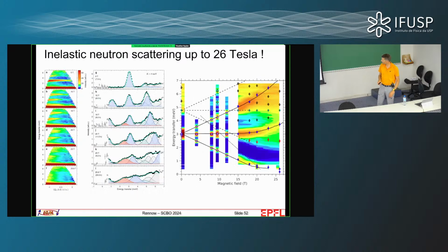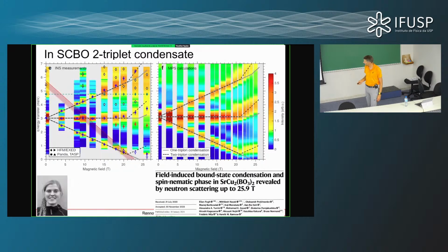We were able to do the neutron scattering experiments all the way up to 26 Tesla. So this is the only experiment on SrCu2(BO3)2 spin half that has been performed for inelastic neutron scattering up to 26 Tesla. And what we see is that we split the energy of this triplet, and we reach down here at around 20 Tesla, and then we can see what happens to the spectral weight. We compare that to the theoretical calculation.